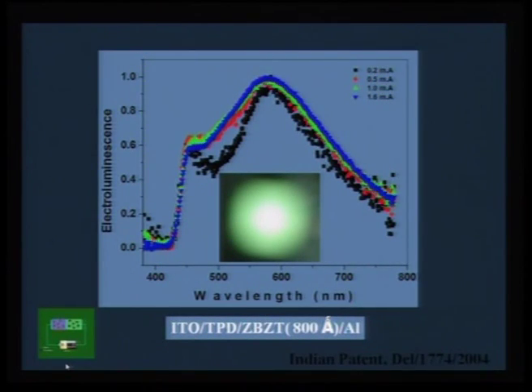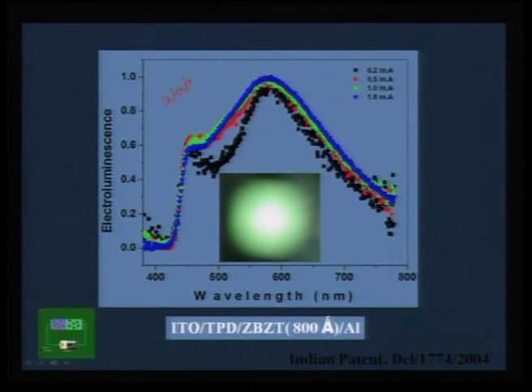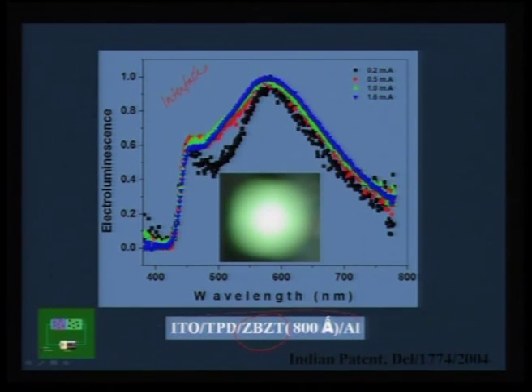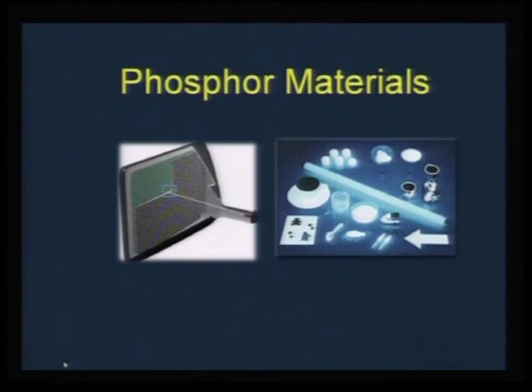There are examples which give us ideas about how to harvest this 25% light output from organic molecules. Also, there is interesting physics when these molecules are placed in solid-state devices — the interface plays an important role. For example, zinc benzothiazole shows a very sharp photoluminescent emission around 500 nm in solution, but once made into a device, it shows strong white light. This is because of the interface chemistry acting between the inorganic and organic material.